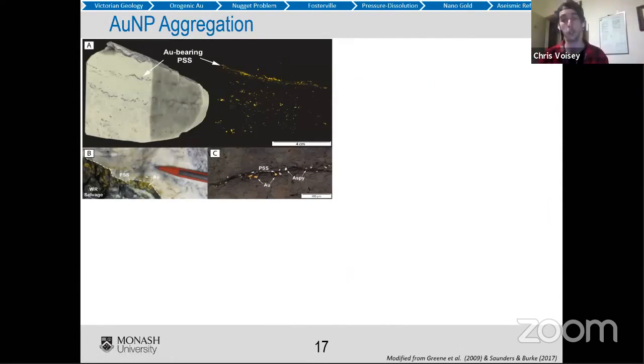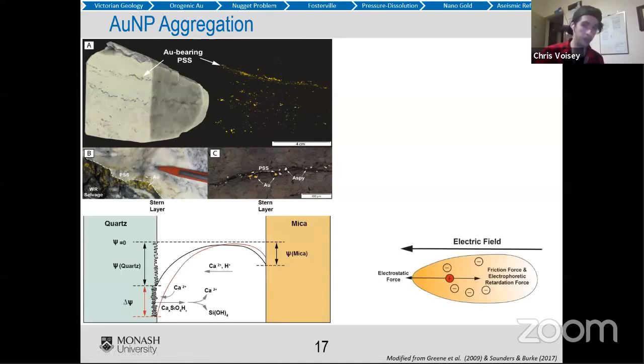Now that we have nanoparticles in a quartz vein, we have to let them grow. So what I have here is the tomography section of the sample I showed you earlier. Here's a very gold-rich seam, some others that live in the vein. This is a wall rock selvage that's been broken along the selvage that occurred underground at Fosterville. So you have a pressure-dissolved wall rock seam and gold dusting it. It's kind of coated in it. When you cut a thin section of that, this is the wall rock selvage here, which has been pressure-dissolved, and you can see gold stuck up in it and a bit of arsenopyrite, which would be the refractory ore that lives inside the wall rock anyway.